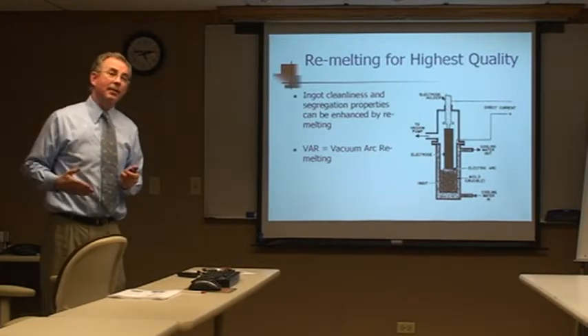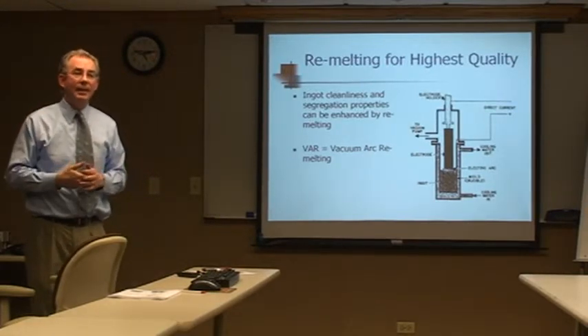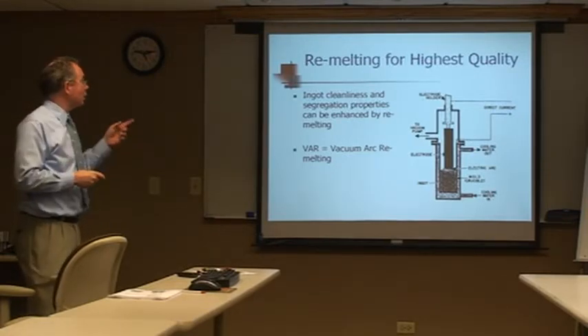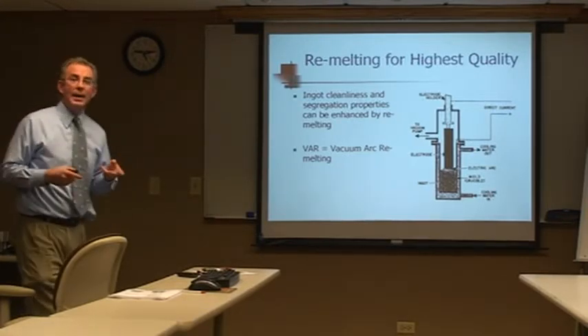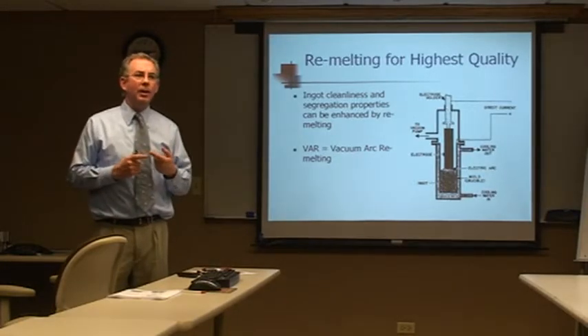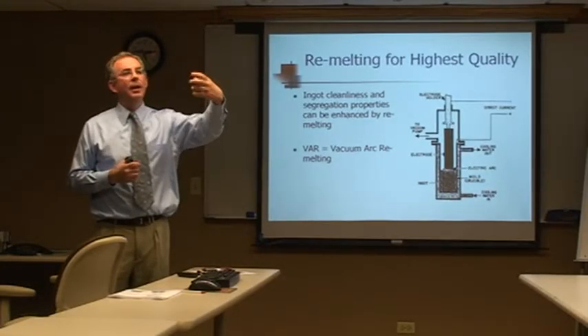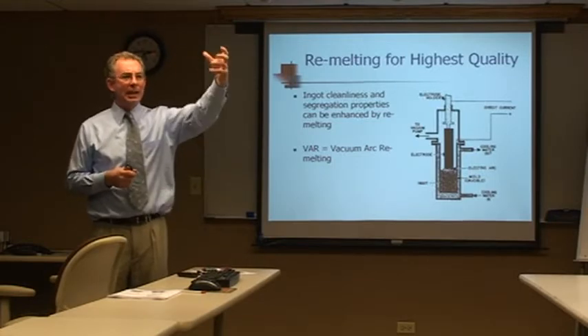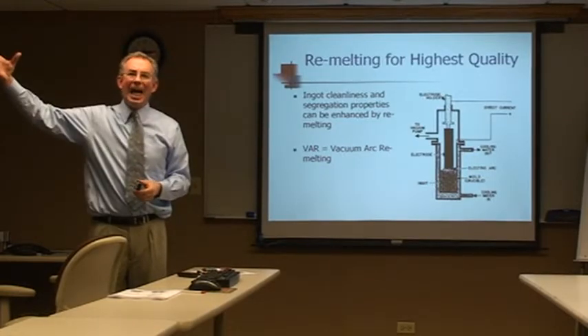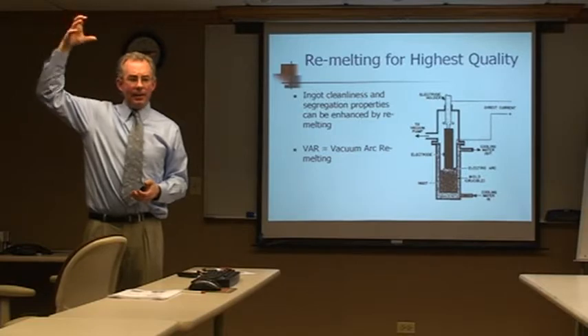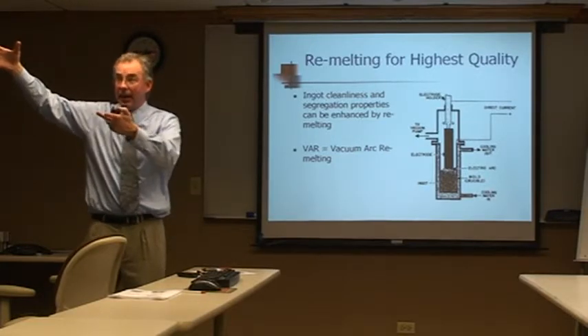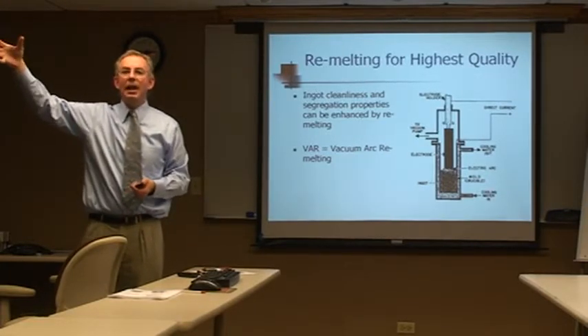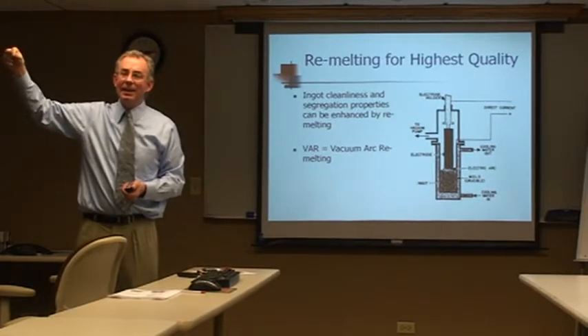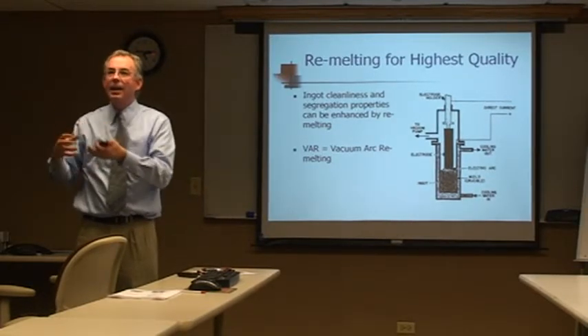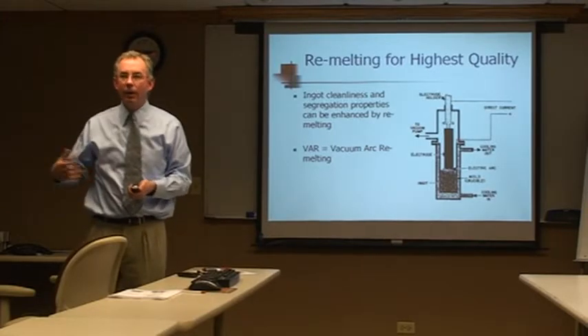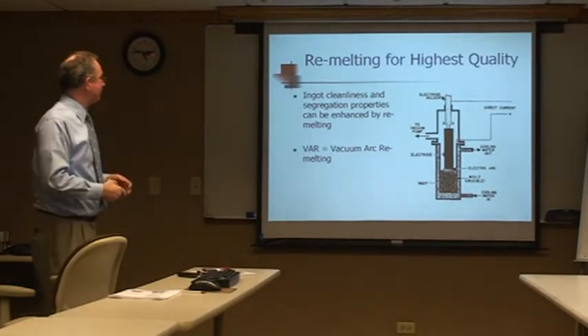So segregation will be greater than what you would get in a remelted ingot, and we'll talk about that in a second. So when you need extremely demanding applications, you can go to remelting, and there are two different ways to remelt. Vacuum arc remelting, where you take an ingot effectively and you remelt it drop by drop in a vacuum, or electroslag remelting, where you take the ingot again, it becomes the electrode, and you melt it drop by drop. Except the steel, in this case, is going through another slag, and as it goes through the slag, it gets even cleaner and then resolidifies below.